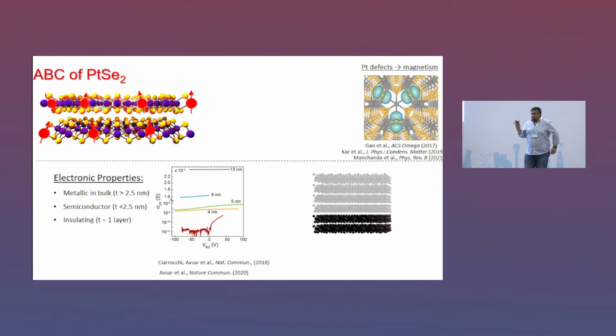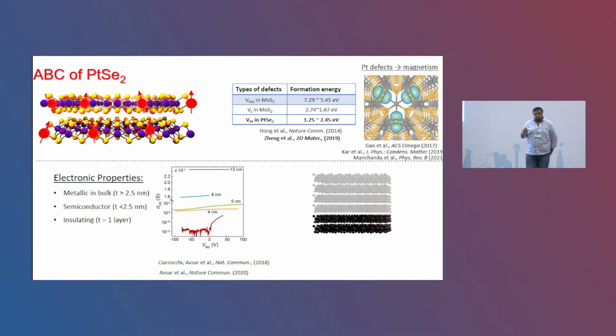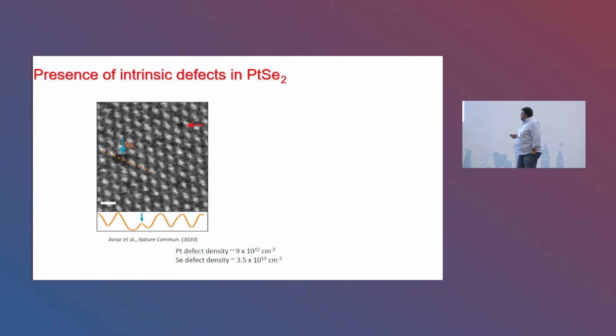But one thing that we were quite interested in with this material was that there were lots of calculations showing that if you can kick out some metal vacancies, in this case platinum, you could kick in some magnetism in this material. And creating this kind of metallic vacancy is slightly easier because of the lower formation energies compared to the semiconductors, where similar physics was predicted. And the question was, do we have this kind of defects? These two-dimensional materials are just surfaces. We generally have lots of defects on these materials. In the case of platinum diselenide, we had a platinum vacancy defect concentration of up to 10 to the power 13.